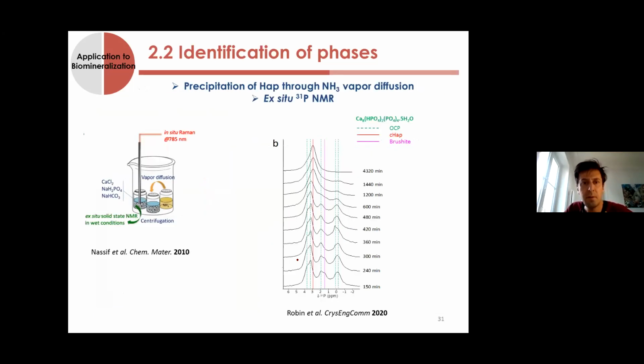So here is an example, for instance, of the monitoring of the precipitation of hydroxyapatite through an ammonia vapor diffusion method. We are looking at the formation of apatite through ex situ solid state NMR - it's phosphorus NMR. With time, you see here that the signal is changing, and it simplifies and goes to a single resonance that is corresponding to apatite. So it means that actually hydroxyapatite is not the first mineral that is created at the beginning of the experiment - it's another phase called octacalcium phosphate, and you see it changing with time into hydroxyapatite.